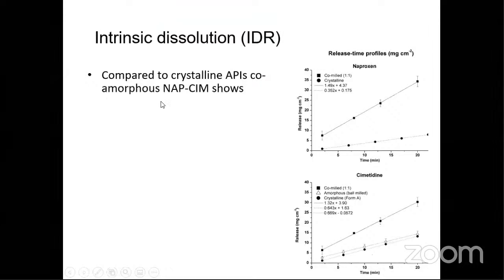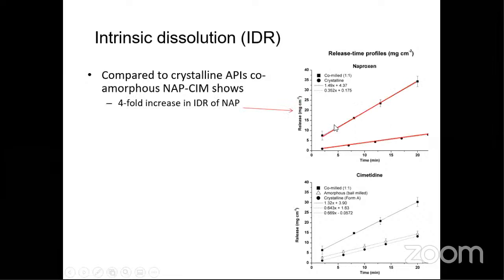More importantly, since we are trying to improve the water solubility of these drugs, we can look at the dissolution rate of these compounds. For Naproxen, the dissolution rate of the crystalline form is here, and this is the coamorphous one - the coamorphous one is much higher than the crystalline one.